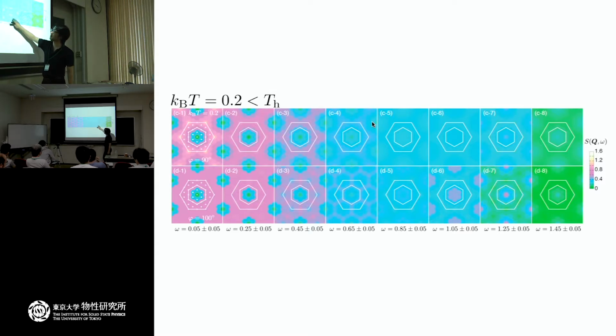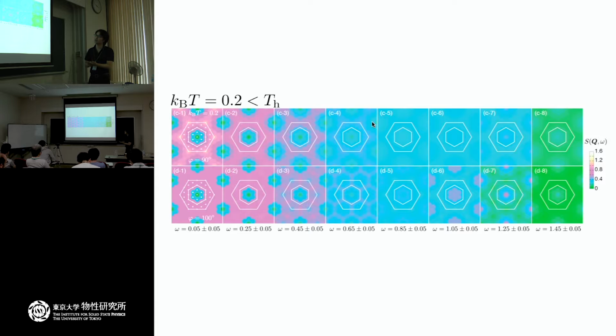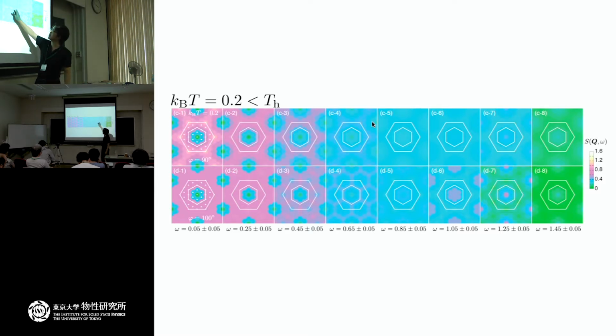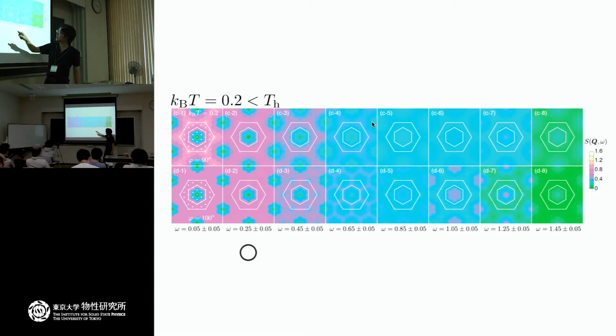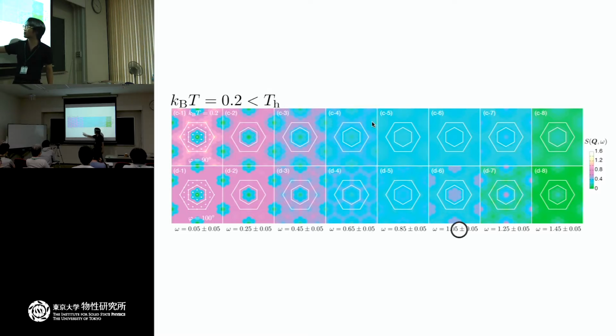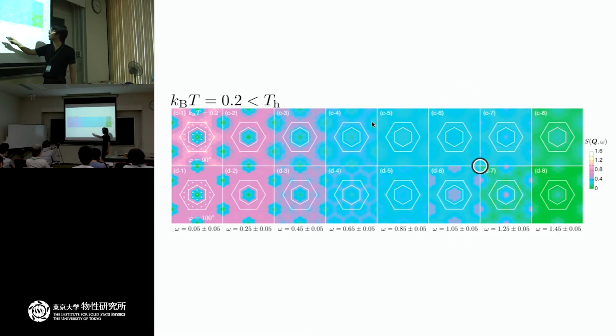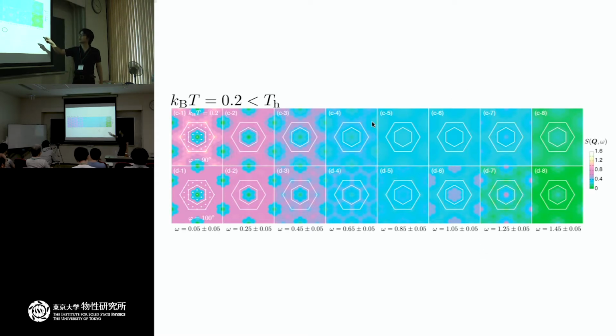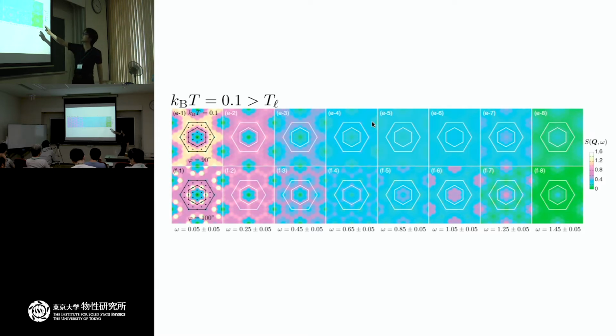From the Kitaev limit to this Kitaev-Heisenberg system with the zigzag ordered ground state, we are introducing less than 10% of the Heisenberg term in comparison with the Kitaev coupling. But still we have a difference, and please be careful, because here the temperature is 0.2, which is larger than the Heisenberg coupling. In addition, here I show you the spectrum from omega 0.05 to omega 1.05, so this energy scale is high enough compared with the additional Heisenberg coupling. But still we have some difference between the Kitaev limit and the Heisenberg limit.